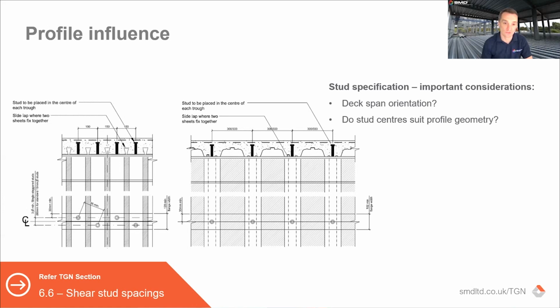So the obvious one is on a secondary beam, so a beam that is perpendicular to the deck ribs: do the stud centers suit the profile geometry. So this is just a couple of images. This is our R51 plus profile. Studs at 150 centers are achievable, 150 or increments of. And then with our TR60 or TR80, you've got TR60 at 333 from stud to suit the center of the rib positions. And with TR80, it's 300. So it's important that you are designing the beam for the right stud centers for that product. And that then, at butt joints where you're staggering, will govern your minimum flange size unless you go into having pairs or more different stud situations.